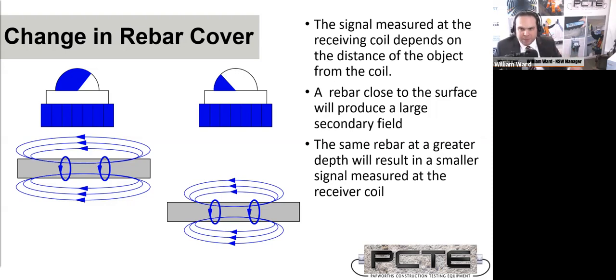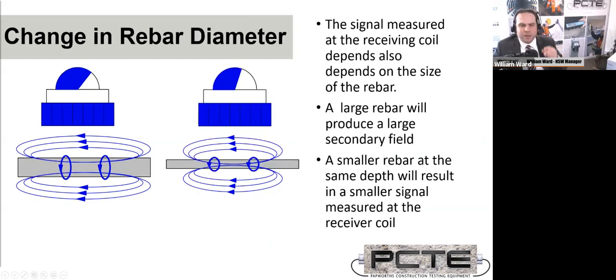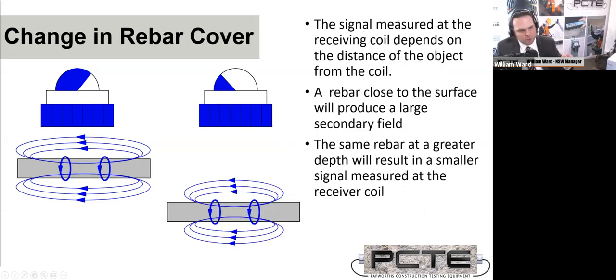So you get a big change by moving the steel bar closer or further away, and you get a fairly small change by changing the diameter at the same height. This is why diameter estimates are an estimate, but cover depth measurement is a measurement with the cover meters.